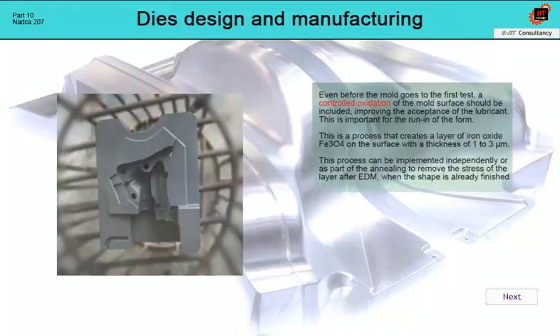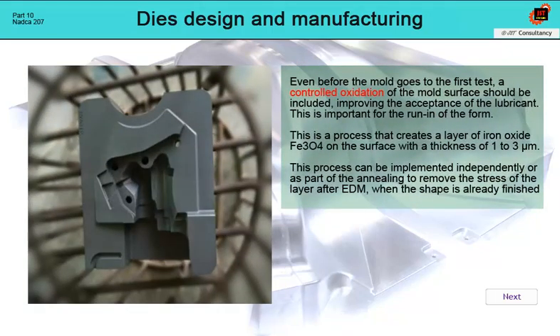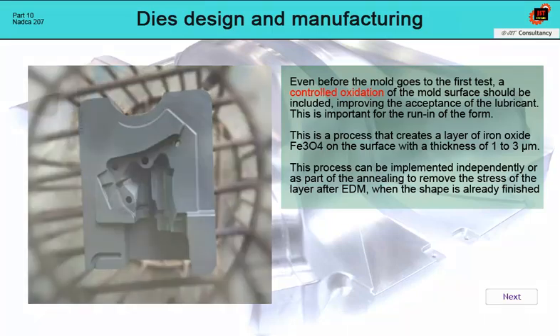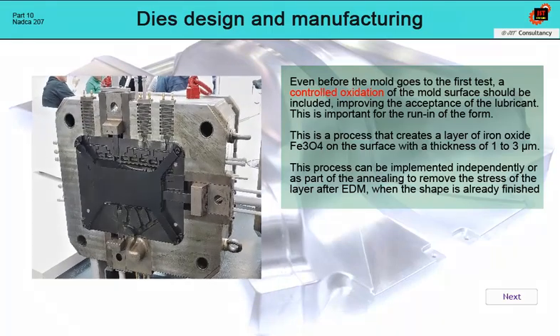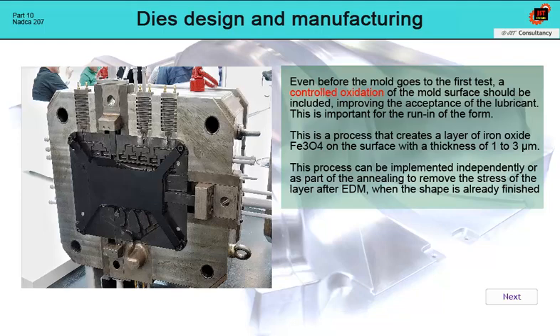Recently, the application of controlled oxidation of the die surface has been significantly expanded. The layer of iron oxides helps to cool the die surface by better absorbing the lubricant. This surface treatment should also be prescribed on the drawing.